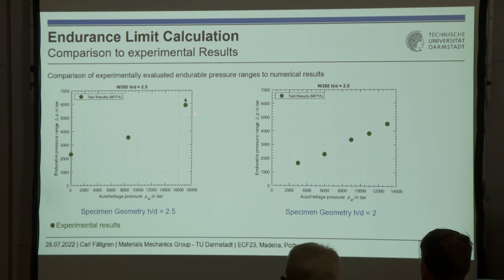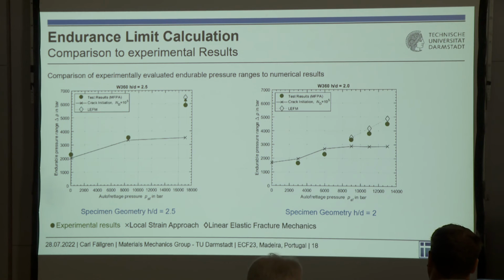and at 17,000 bar autofrettage, at this highest point on the left side, I've added this arrow because we could not determine the endurable pressure range experimentally. So in the next step, the solid line marked with the X's, this is our estimation for crack initiation. On the left side, you see it's below the experimentally obtained value, which is also what we expected. You also see that it's pretty close to the specimen autofrettaged at 8,500 bars.